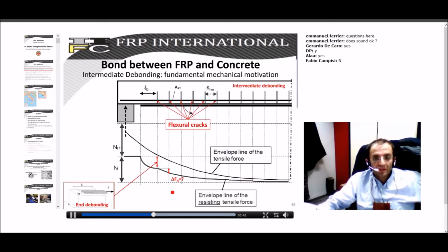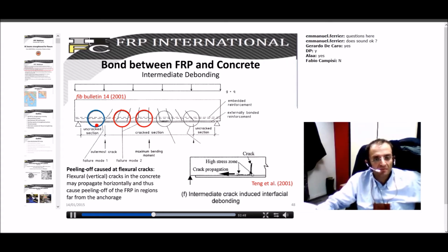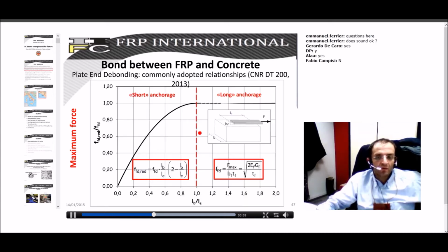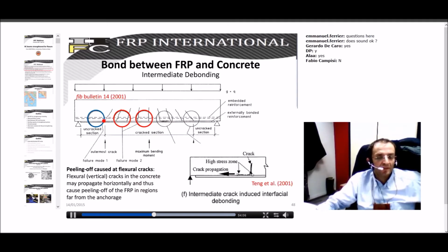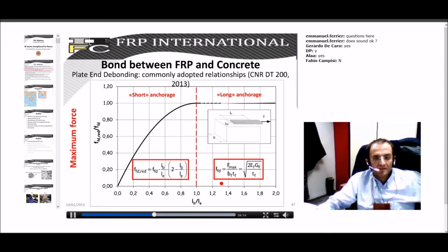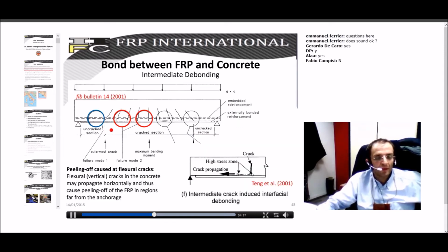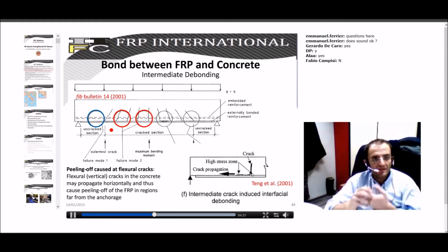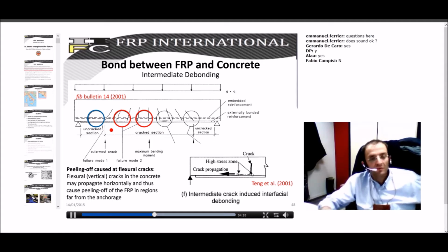Now we have to approach the intermediate debonding. So it is more or less clear how this end debonding works. We have to evaluate the FD maximum according to this relationship. We have to evaluate the transfer length, LE, and the actual bond length, and you can evaluate how much is the maximum FD which can be applied here. So it's easy. You can evaluate FD and compare with this maximum strength. If the stress is lower than strength, you have no problem with the plate end separation. Otherwise, you have to consider that plate end separation can occur, and then you have to take the appropriate countermeasures. But now let's move on to this more complicated and more peculiar behavior.